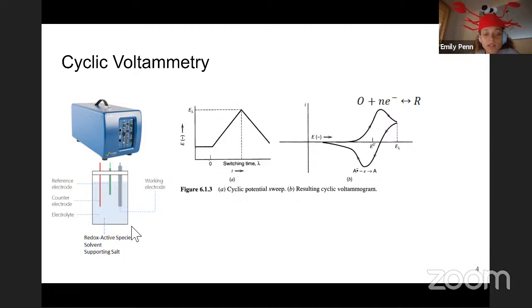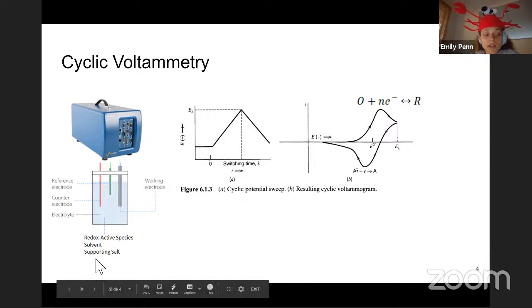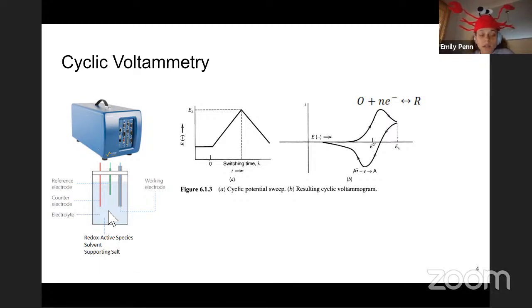For non-aqueous systems, we're working with a silver quasi-reference electrode right now. There's also different options there. And then for a counter electrode, we normally use a platinum wire. And then in your solution, you have your redox active species at some concentration, dissolved in a solvent. And then you have a higher concentration of a supporting salt, which provides ionic conductivity to your solution.